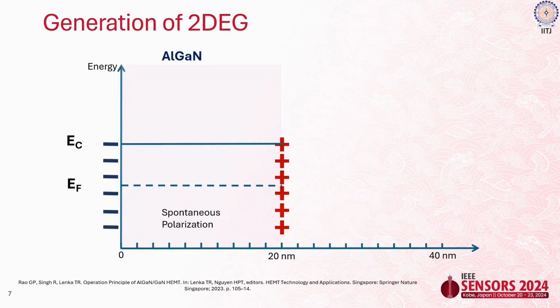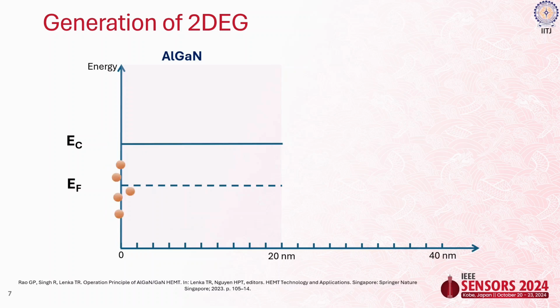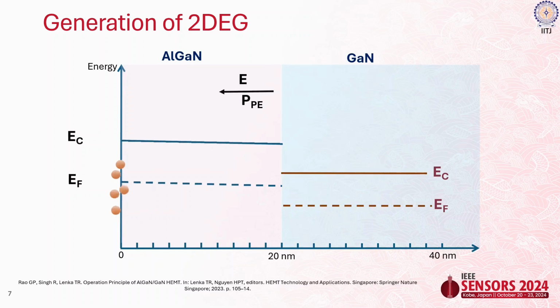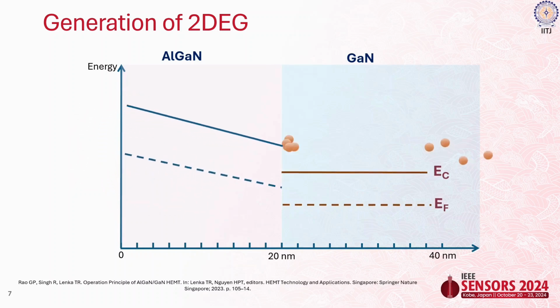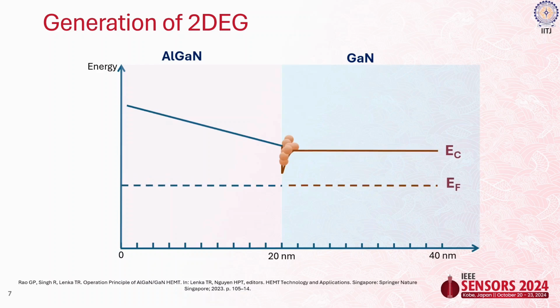So how does this 2D electron gas form? Due to the spontaneous polarization of the AlGaN material, the electrons from the top surface move towards the interface, and due to band bending and aligning, we see that at the interface of AlGaN and GaN, a charge trap forms, and in this trap we have abundant electrons that can move only in X and Y direction. If this one is the top, and if we go bottom, at the interface they can just move along the interface, not up, not down.